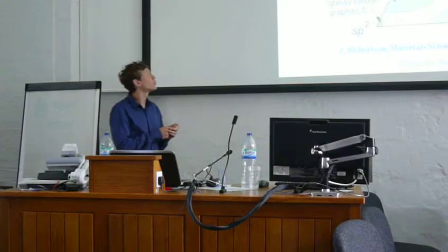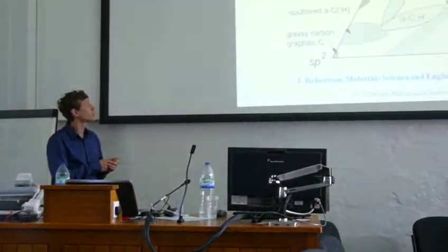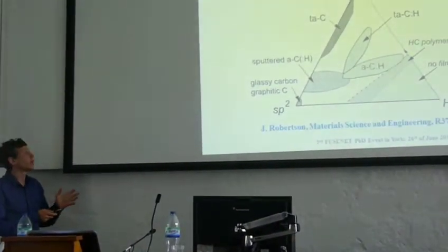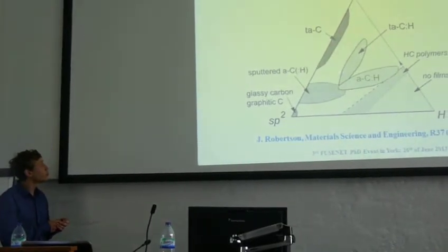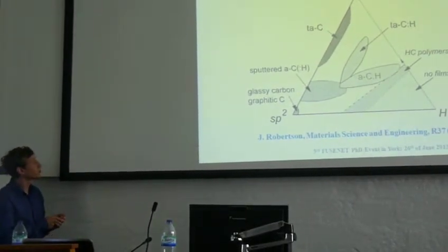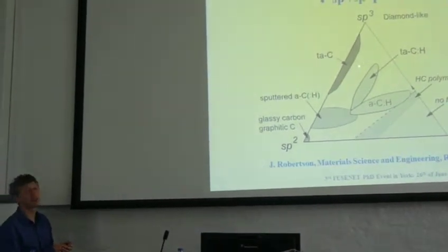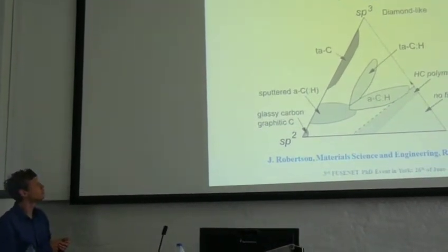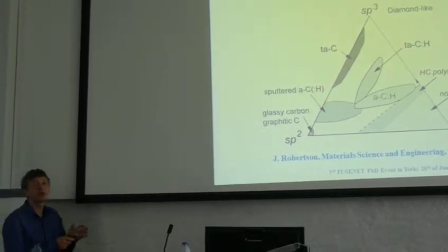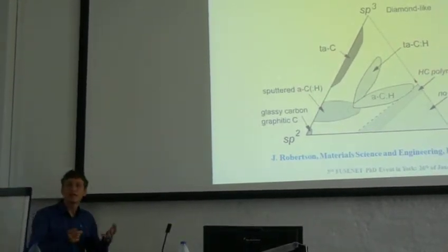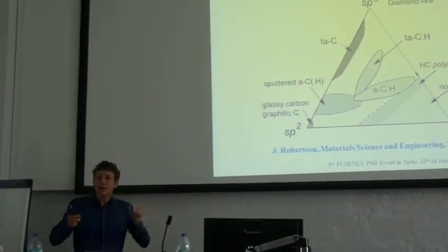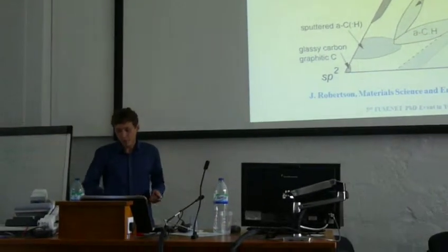Okay, let's take our diamond materials, which is pure sp3. We put it in the plasma, it appears again here, and then we heat it up. So it starts moving, as Raman spectroscopy says. Basically, we have an increase in the negative ion yield, and then a decrease. So somewhere there should be an optimal point for the highest negative ion yield possible.